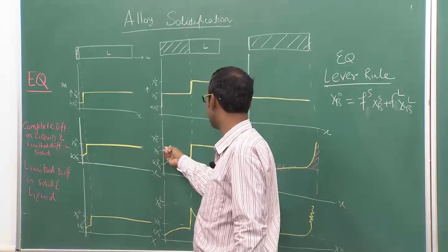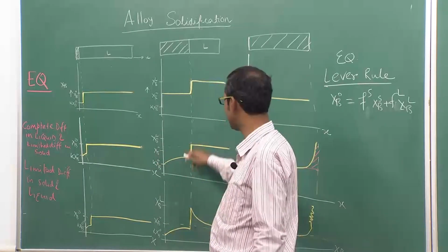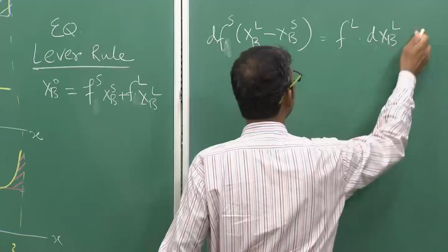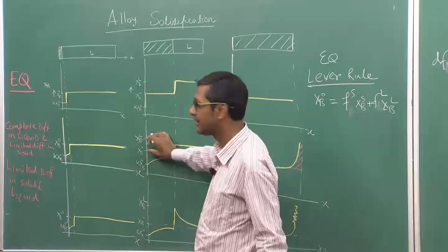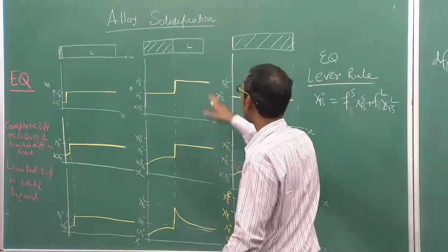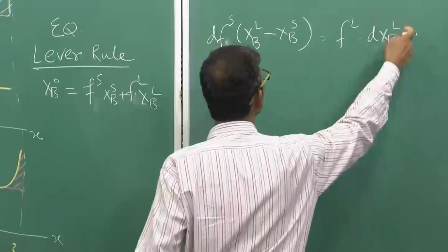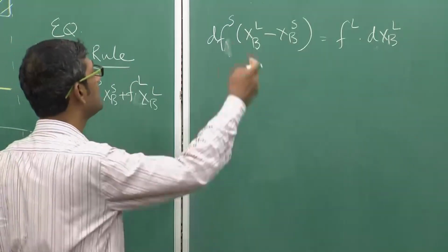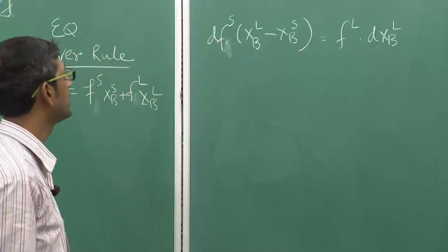So remember this composition is higher than xb0, because there is a build up, or an increase, in the liquid. This is the increase, dxl, and the fraction of liquid, how much liquid is left over, must be multiplied with that. So this is the solute rejected into the liquid, and this rejection is equal to the change in the solute concentration in the liquid.